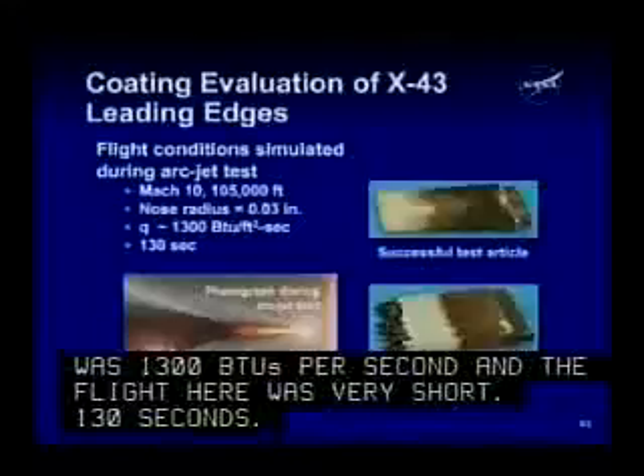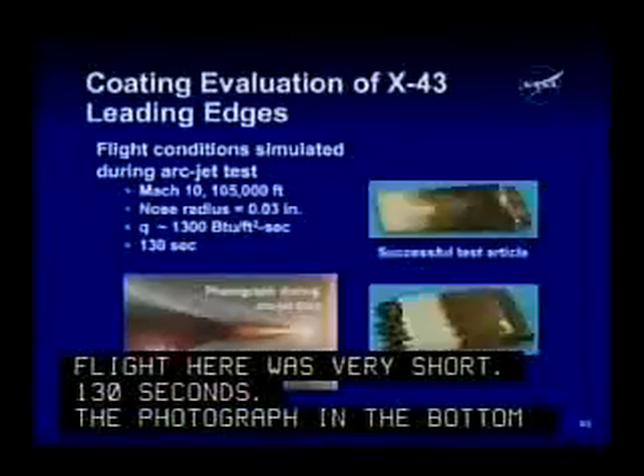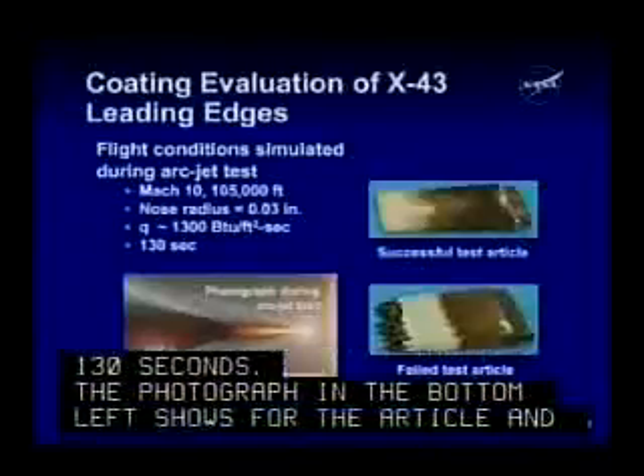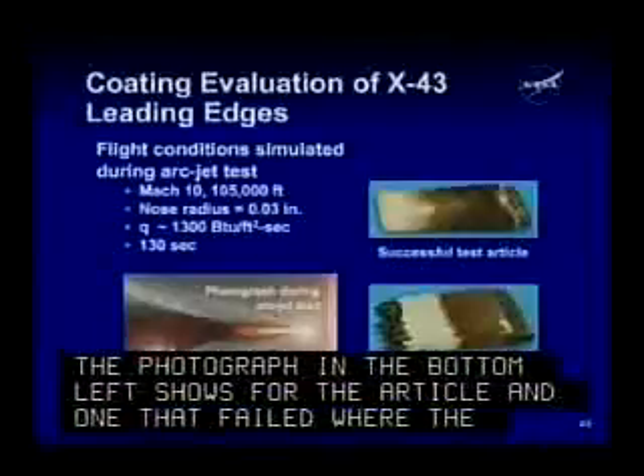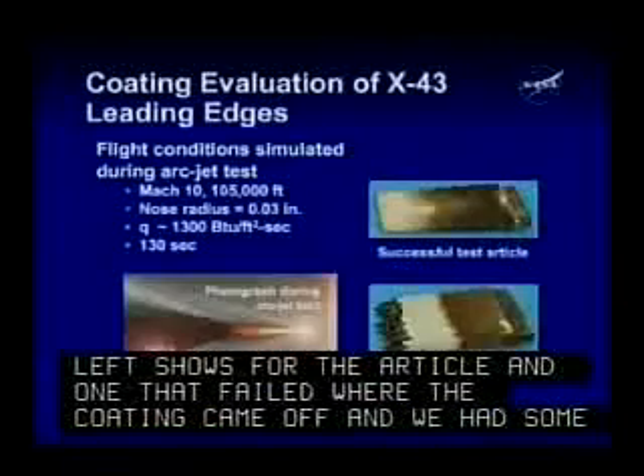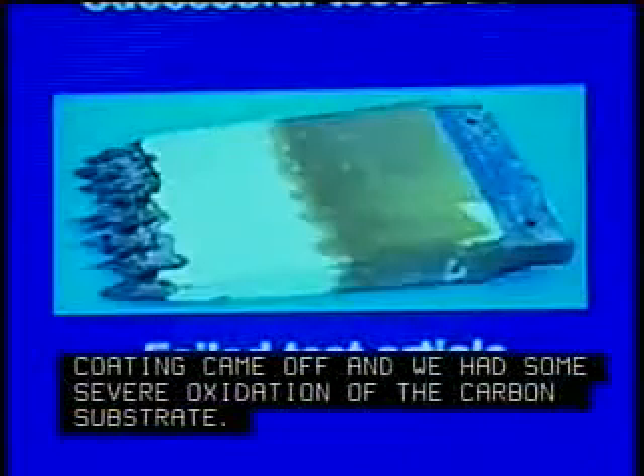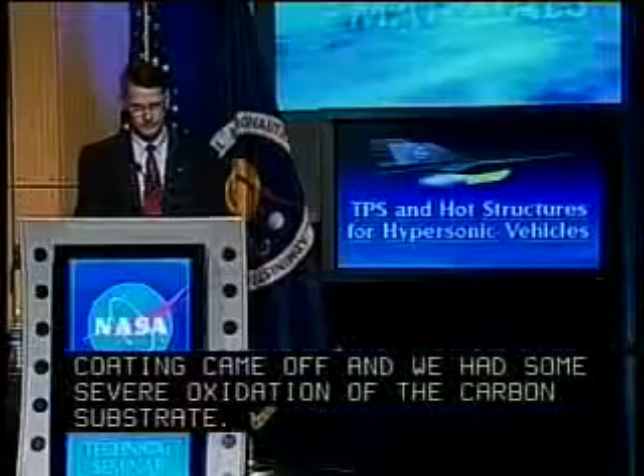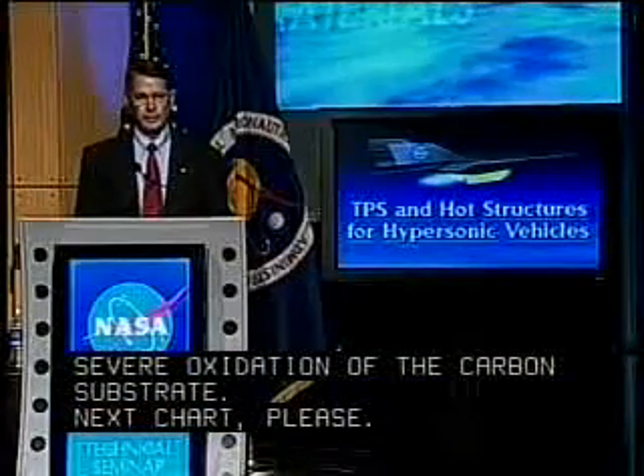The photograph on the bottom left shows a leading edge test article during arc jet testing. You can also see a successfully tested article and one that failed, where the coating came off and we had some severe oxidation of the carbon-carbon substrate. Next chart, please.